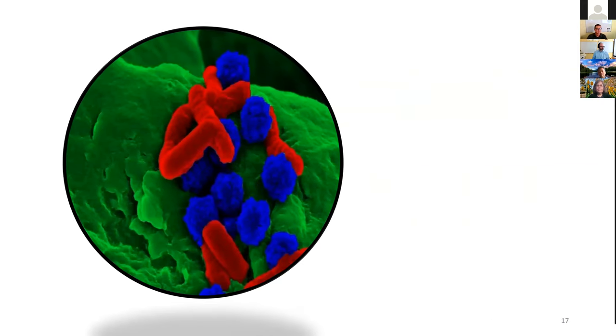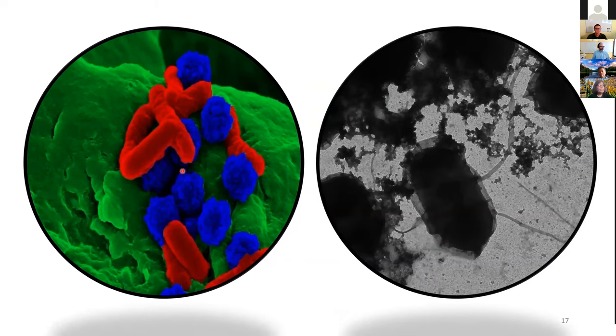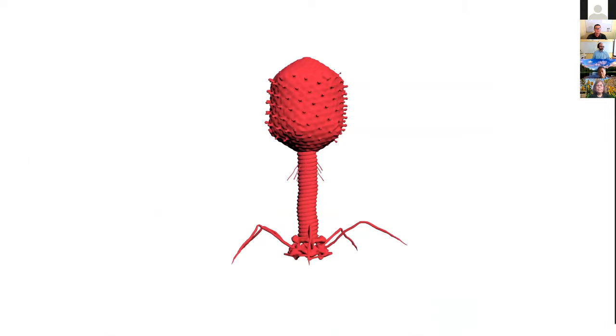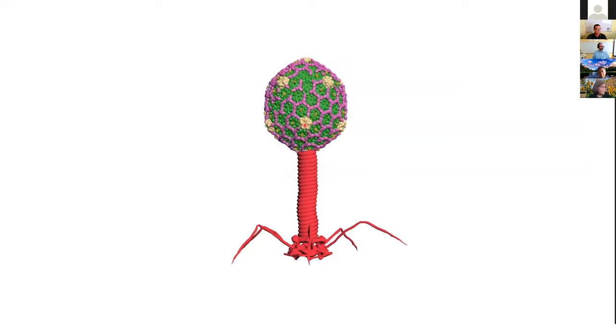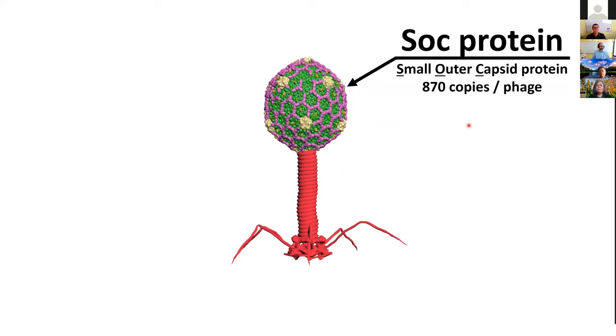Here are some larger particles that have bound onto these red E. coli. Here are nanoparticles that have bound onto this E. coli. I'm going to give you a quick run through of how we did this. We essentially bound onto these purple proteins, which are called the SOC protein. There are 870 copies of them. These are the ones we modified with an unnatural amino acid. Having the unnatural amino acid with an alkyne group on it allows us now to bind onto an azide-containing nanoparticle.